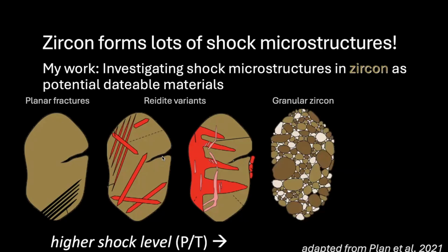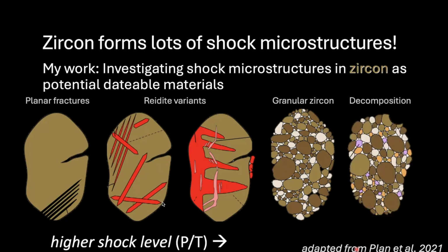With really high temperatures and pressures, we don't exactly know which level, zircon also becomes granular. So each of those granules has a crystallographic orientation that differs systematically from the other granules. I'm going to talk about that a lot more later. At the highest temperatures, zircon and reidite are both no longer stable. So for reidite, this is above 1200, or actually, I think it's above 1673 for zircon at ambient pressure. That's centigrade. What happens is zircon and reidite are not stable. They decompose into mixtures of zirconia and silica, which may be crystalline as various polymorphs, or they can be liquid depending on the specific conditions. And I will show you that phase diagram later.